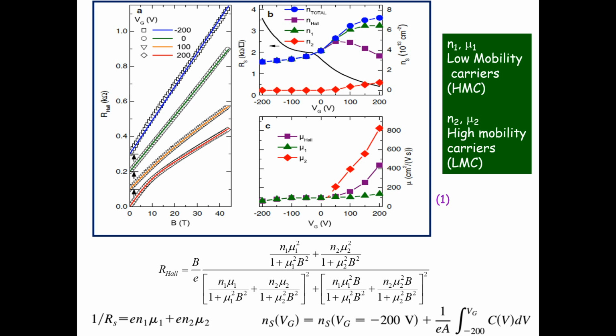And as you increase the gate voltage now, come to 0, it remains linear, and when I go to 100 and 200 volts positive, you start seeing the signs of nonlinearity here. We have data now with much closer steps in this range up to 10 Tesla, and this is exactly reproducible, the nonlinear behavior, and there is no hysteresis. So I cannot say that it is some sort of an anomalous Hall effect and there is hidden magnetic order in the system. We don't have any evidence for magnetic order in these samples.